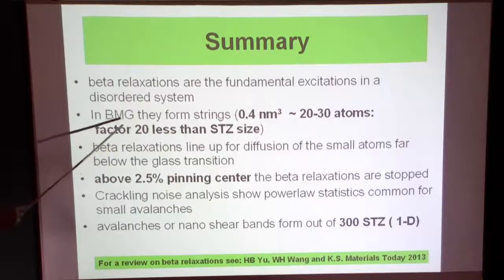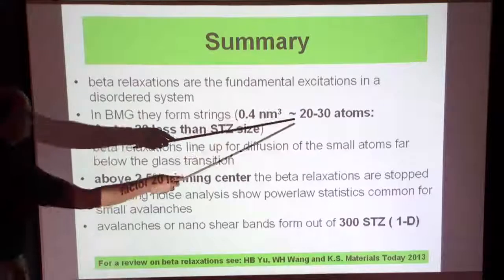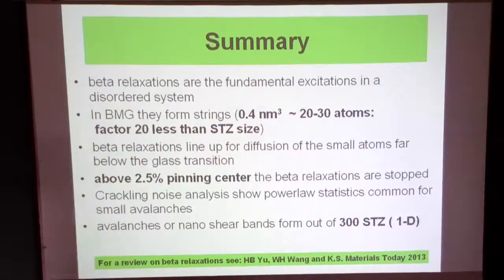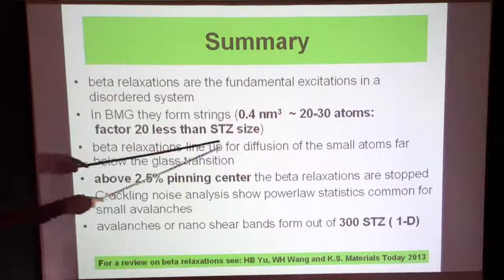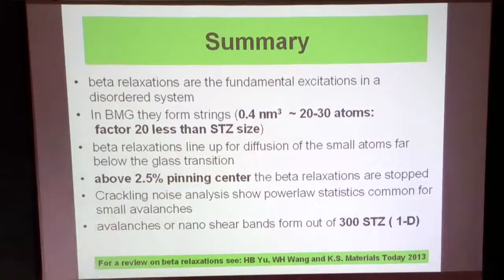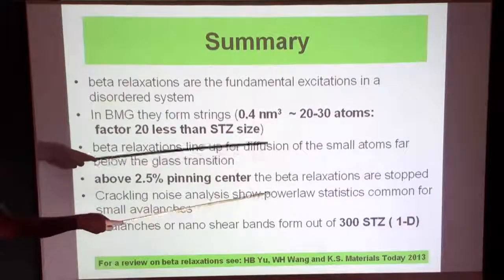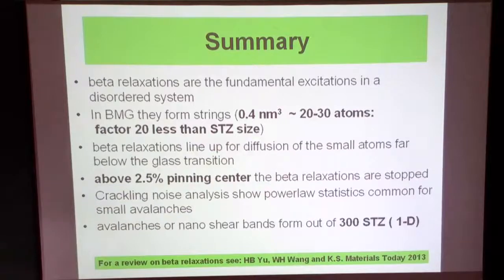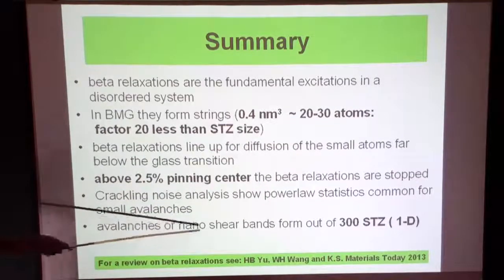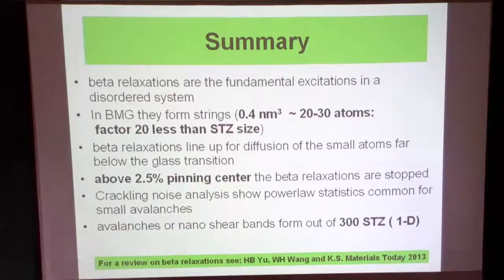And these in the bulk metallic glasses, we think we have that of a size of 20 to 30 atoms, at least a factor less than these plastic events. And they line up for diffusion. I didn't show you that for the small atoms, how this works. Pinning center, Itamar showed a little bit of this work in his talk during the conference. And the crackling noise analysis gives you at least these statistics similar to the small avalanches. And then if you calculate how much slip you have in one dimension of an avalanche of this size, we need about 300 in a row, which is quite a big number already for making 50 nanometer avalanches. And then the avalanche crosses over to really a nano-shear band. Okay, that's it. Thanks very much.